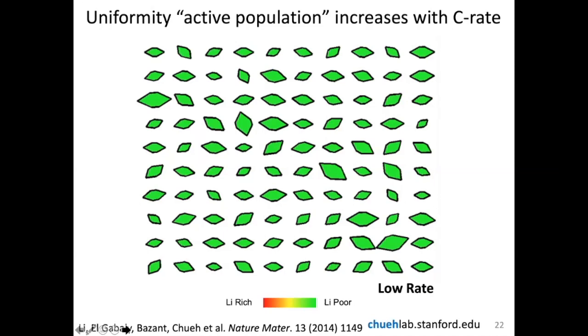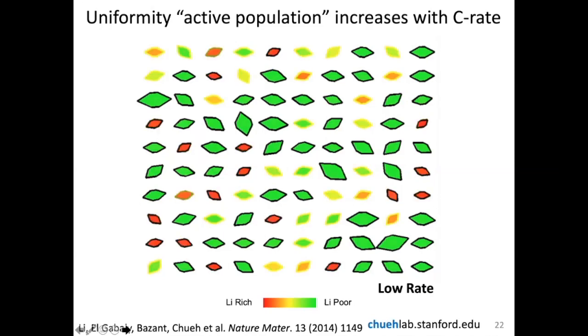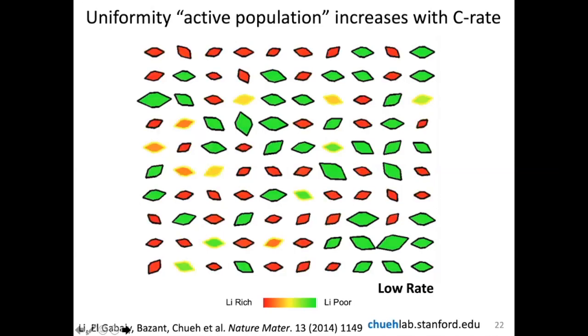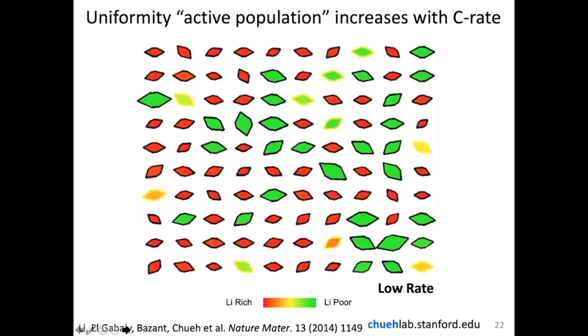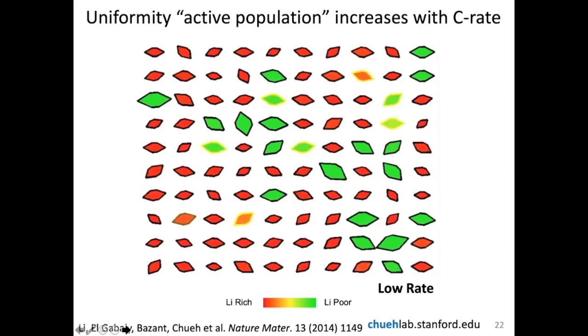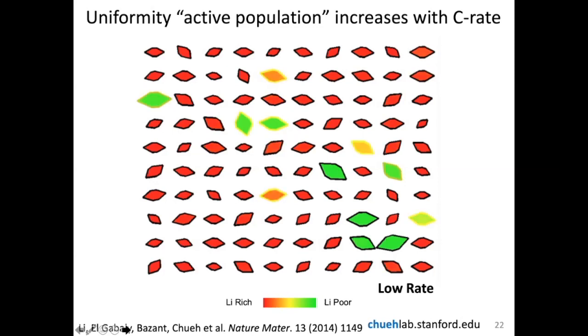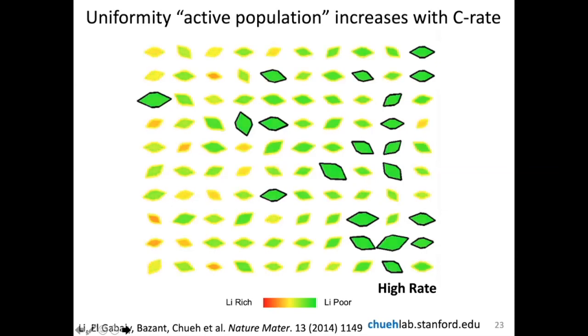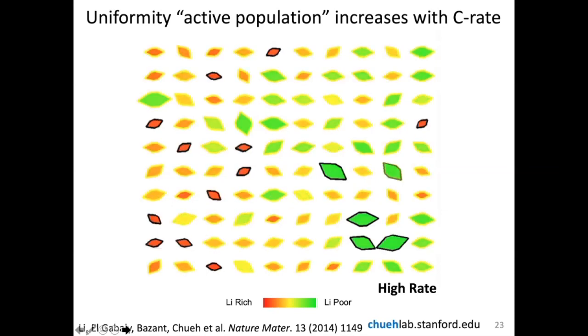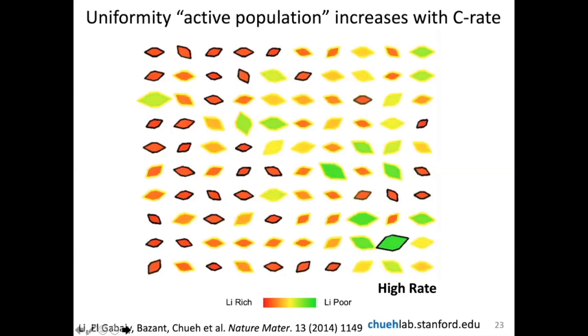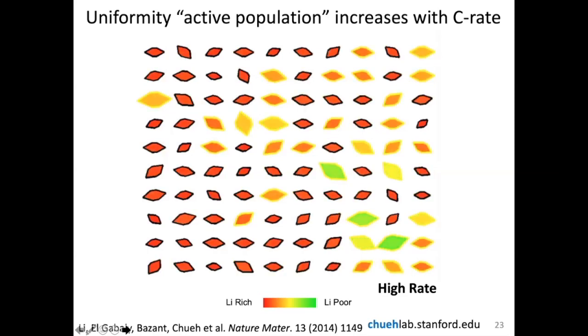So what's happening here? Well, let me first show you a movie. This is a simulation we have done. At low rate, you have this very mosaic behavior, which means that the extraction is proceeding non-uniformly. So you have what appears to be a popcorn effect. This is exactly opposite of NMC. So this happens at low rate. When you go to high rate, the battery actually becomes much more uniform. So again, the behavior is entirely opposite of NMC.